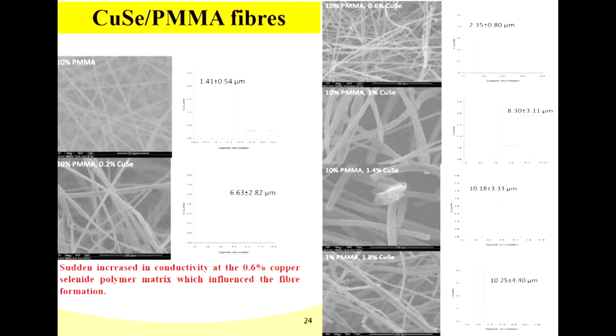And as you add the amount of your nanoparticles into the polymers, you're also introducing some conductivity. At a very small amount of copper selenide being added, we realize that that's where you've got the highest conductivity, as opposed to what you normally expect. This has not been explored further, but it's a very strange phenomenon. You would expect that increasing the amount of copper selenide would increase the conductivity, but at the same time, this increased conductivity at 0.6 copper selenide is what caused the fiber diameters to be even smaller compared to the rest of the increase being observed there.